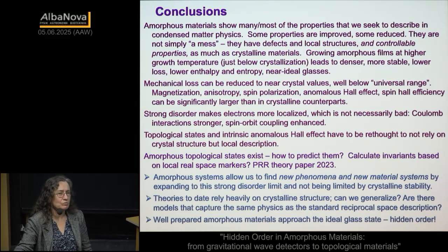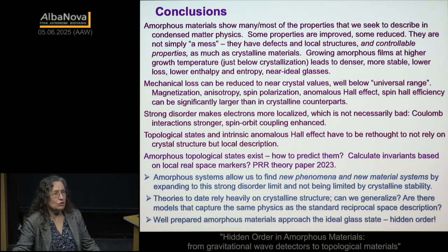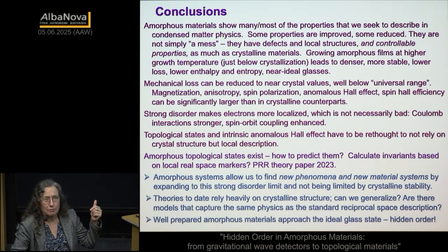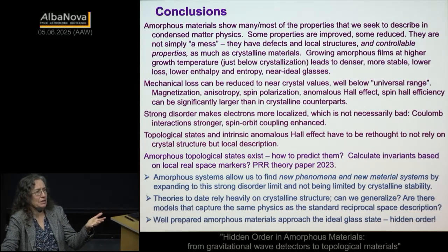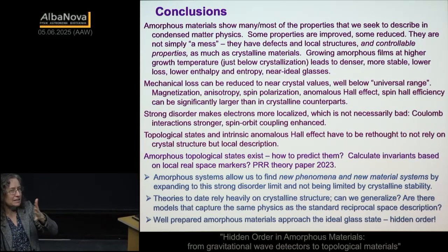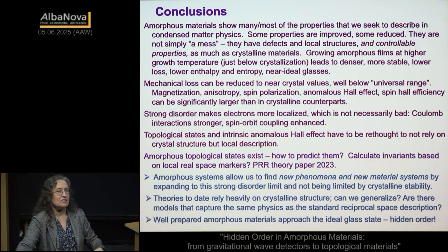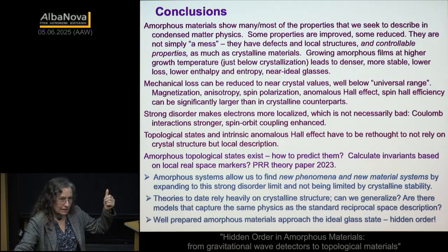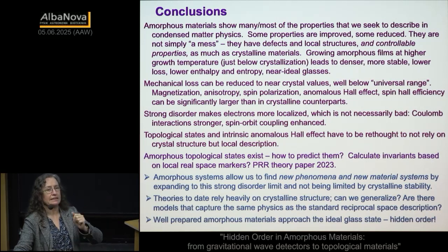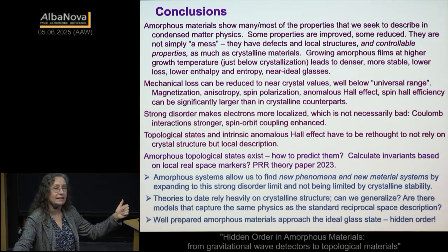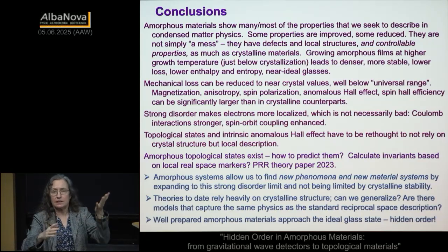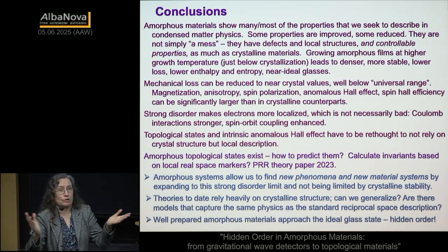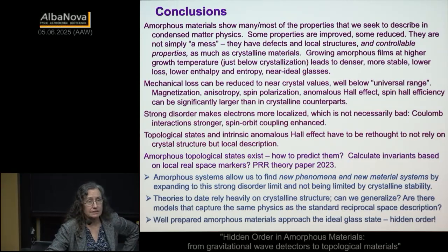You have to have a dipole moment to have a dielectric loss. So where is the dipole moment in a monoatomic material like silicon? Why does it have a dipole moment at all? So maybe a dangling bond makes sense. Experimentally, it correlated with dangling bond density, which the mechanical loss does not. Mechanical loss just literally crisscrosses. It just doesn't work to try and correlate it with dangling bond densities.